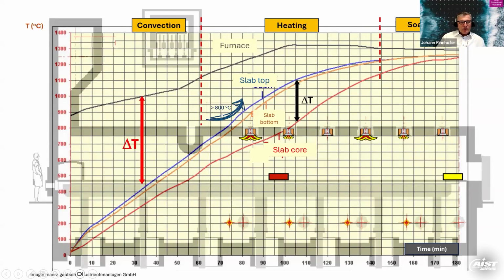On the other hand, we want to have a very short period of time in the heating zone. So the residence time in the heating zone should be very, very low if possible, because we get this high oxidation in the area higher than 800 degrees Celsius. So it's a bit of a catch-22. On the one hand, we want to have a high temperature here in the furnace to enhance the heat transfer. On the other hand, we want to minimize the scaling, the oxidation. So it's a very fine line we walk there. So how do we design this process in the end?